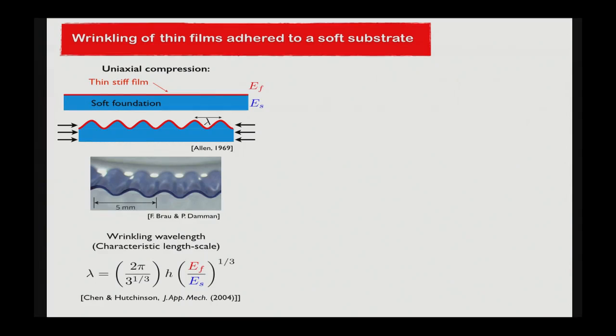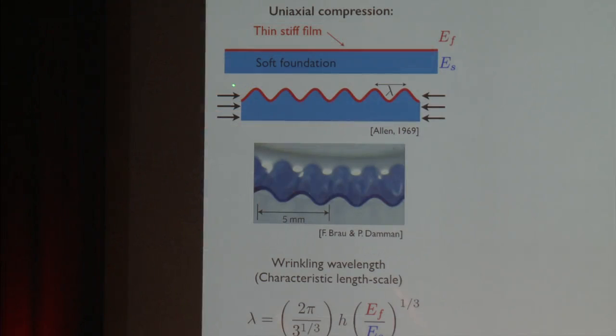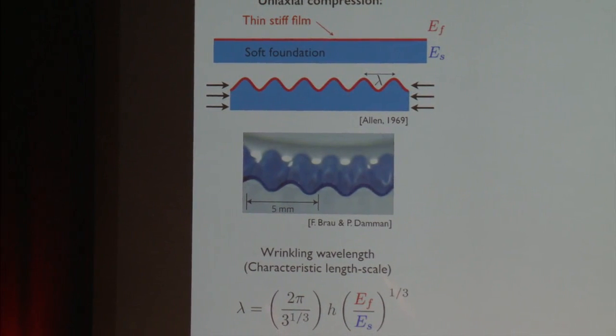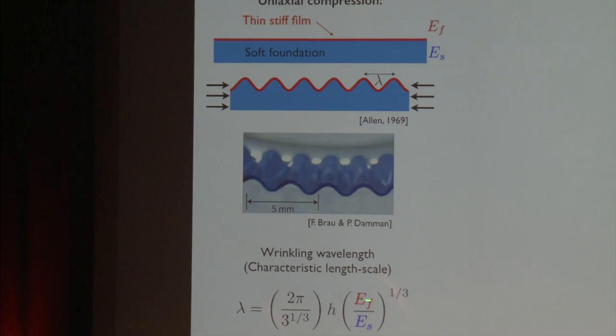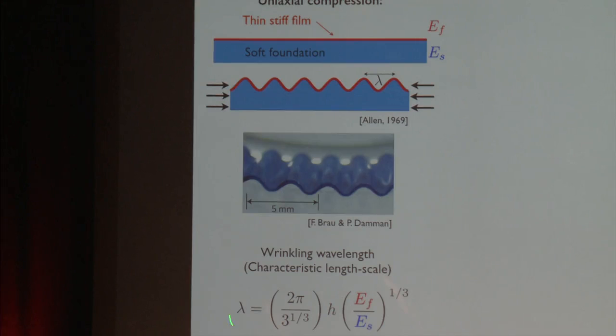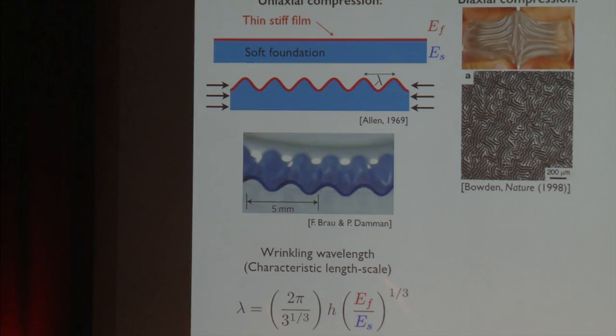When you apply a compressive load, the thin film, if it was by itself, would like to go into the first buckling mode, but it's attached to the substrate, so that would cost too much energy. And instead, there's a characteristic length scale that gets selected, that looks like this in real life. It has been calculated exactly, so the solution for wrinkling dates back to the 60s, when people were thinking about sandwich panels in structural applications. And so the wavelength for wrinkling depends on the ratio of the stiffnesses of the film and the substrate to a power of 1/3. It goes linearly with the thickness of the stiff film, and there's a prefactor that can be calculated exactly. So this is for uniaxial compression. When you apply loads biaxially, so you have loads in two directions, you can get more complex patterns.